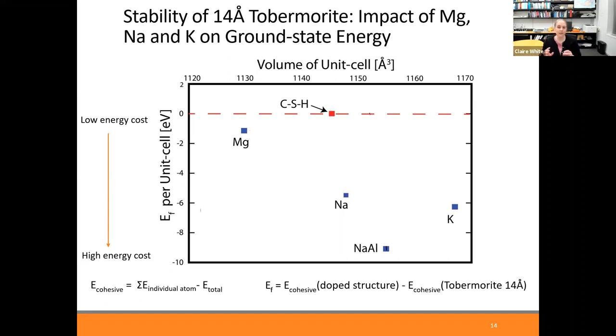And so what you see on this slide here is if you replace a calcium for a magnesium in the interlayer, it is less stable. If you replace the same calcium with sodium, it's even less stable compared to the magnesium. Likewise, if you do a sodium substitution and also an aluminium for a silicon site, it ends up down here. And then potassium's over here as well. I'm not going to go into the volume for the time being.